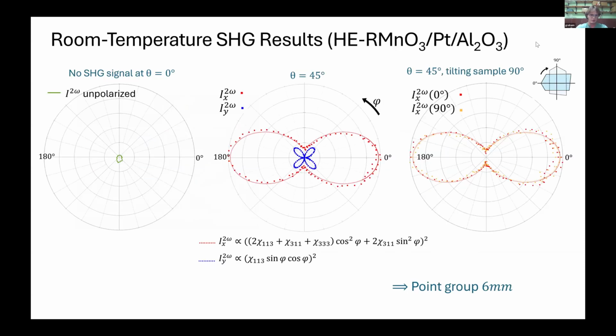And then here we have the actual measurements at room temperature to confirm that this is 6mm and not orthorhombic. So we have the expected polarimetry at oblique incidence, and we have to do some other checks to rule out other point groups, so no signal at normal incidence, and the polarimetry does not change if we tilt the sample. And these are things you can verify if you play around with the tensor transformations.